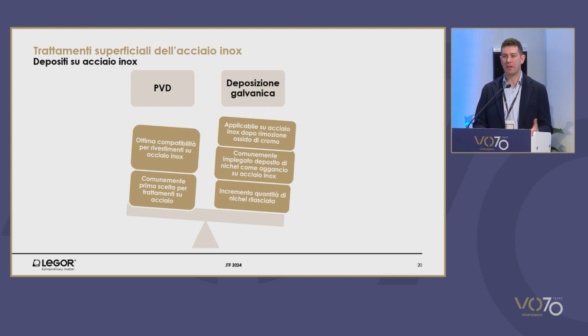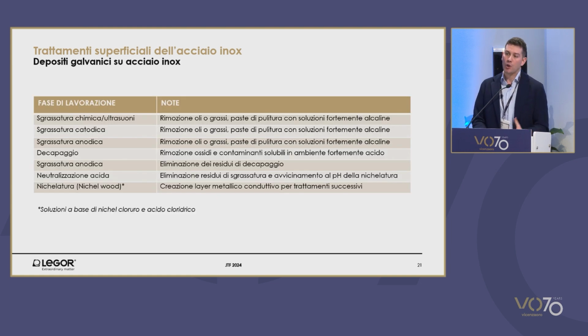With electrolytic deposition, you have to have conductive substances. The presence of an oxide is indeed an obstacle that can be solved by means of scratching the material and preparing the surface before the treatment. Usually different layers of nickel are used.